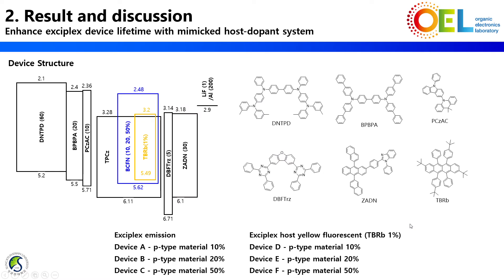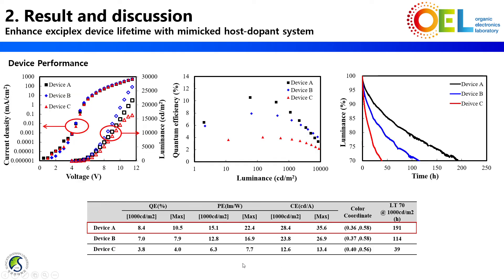Next, device lifetime testing was carried out. This test is divided into the exciplex emission device part and the exciplex host yellow fluorescence device part. The P-type host concentration ratios were 10%, 20%, and 50%. First, in the exciplex emission device part, device efficiency followed PLQY. The dispersed exciplex-based devices showed large efficiency enhancement, as in the previous work.